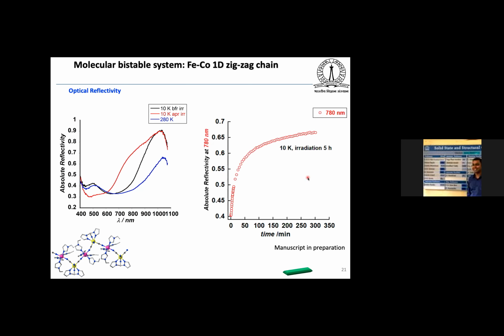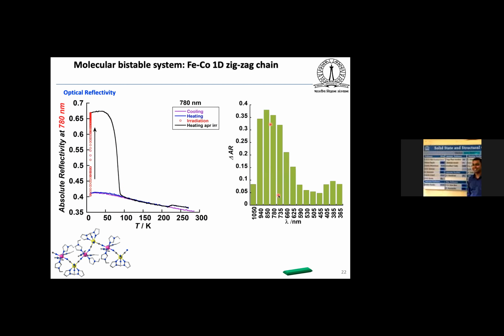You can see that after almost 5 hours of light irradiation, the system almost reaches the saturated value. After getting the saturated value, we check the thermal stability of the photo-induced metastable state when we increase the temperature from 10 Kelvin to 250 Kelvin using a 0.2 Kelvin per minute sweeping rate. And you can see the photo-induced metastable state relaxes back to the diamagnetic ground state at roughly around 90 Kelvin. There is also a small artifact you can see, which is also a signature of the photo-induced effect at high temperature. And you can see from the histogram that 780 and 800 nanometer light are the most efficient lights to convert the diamagnetic state to the paramagnetic state.